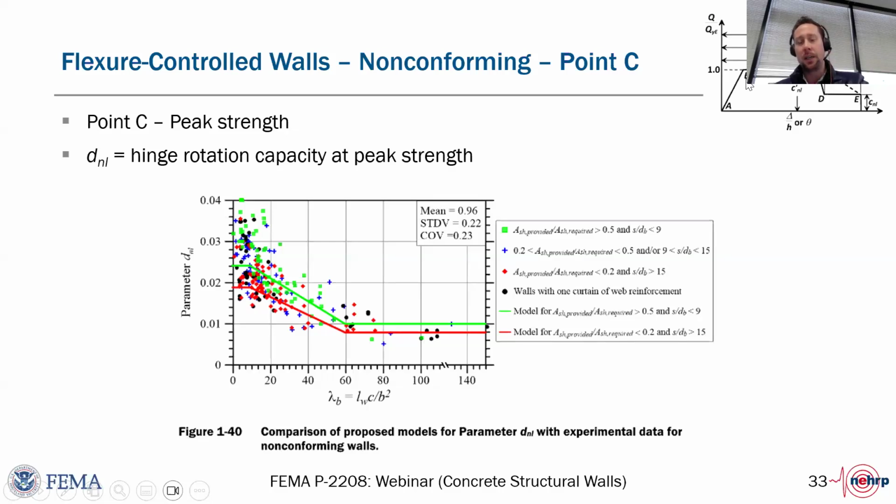And that's not only considering the strain hardening in the steel, but all other sources of material overstrength that lead to that. Interestingly, we found, at least this is what was reported by Saman and the folks doing the data analysis, that the 1.15 factor corresponded better to the observed strength in the walls than trying to model a fiber model with strain hardening in the steel. Again, there are multiple factors at play, so it's not just the strain hardening.